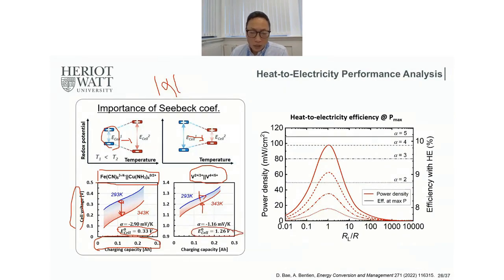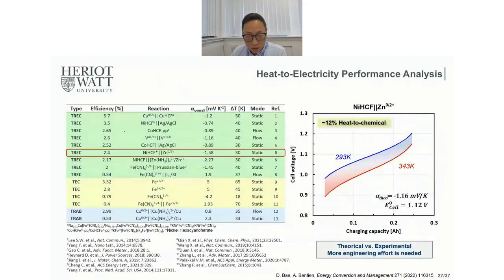So our goal is finding something in between, having a very high cell voltage and at the same time a very high Seebeck coefficient, the thermogalvanic coefficient number. Let's see this chart on the right side. If we have a high Seebeck coefficient or thermogalvanic coefficient, both the conversion efficiency, this is the efficiency at the maximum power point, and the power density can be as high as possible. So that is why we highlight a high Seebeck coefficient for the chemical system.